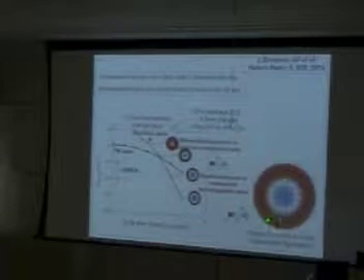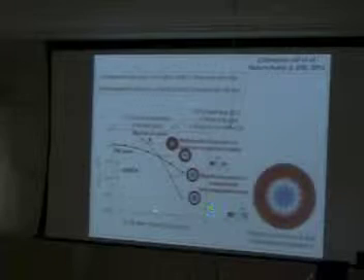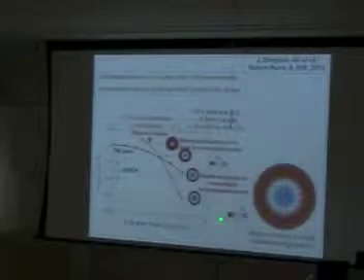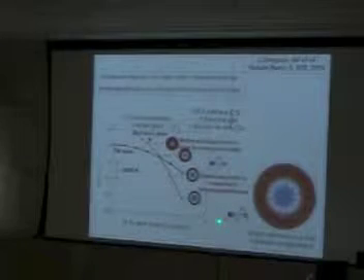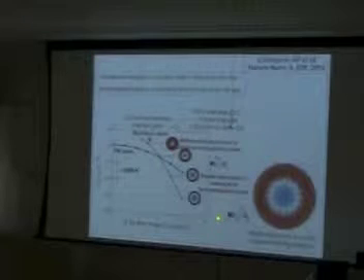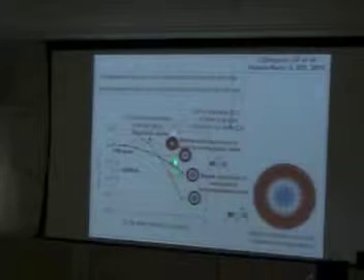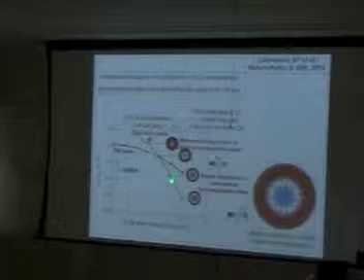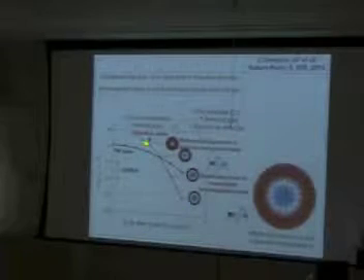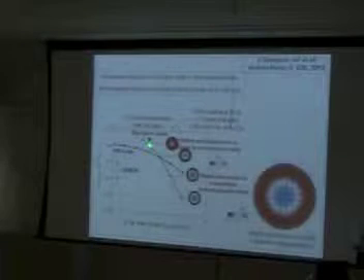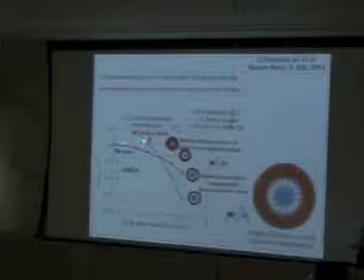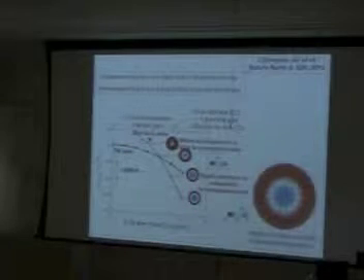So on this curve, this is D, a relatively small value of D, corresponding for example to one monolayer, referring to the work by Wiesendanger, would correspond to a D in this range. For two monolayers, this corresponds more or less to this value here, about 5. And this value corresponds to 3 or 4 layers of film, a little less than 1 nanometer.